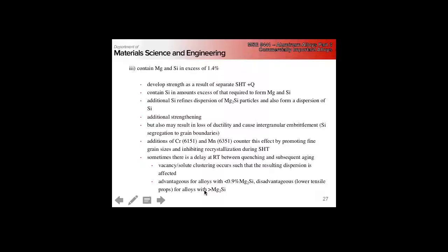The third class raises things up a little more, with a bit higher silicon. Again we use these after a separate solution heat treat and quench, and the excess silicon helps us get a finer dispersion of the Mg2Si particles, which are our primary strengthening mechanism. But we get higher strength at the trade-off of loss of ductility. This extra silicon, while it helps get a finer, more homogeneous precipitate structure, has a tendency to segregate to the grain boundaries, which can give us a significant embrittlement issue.